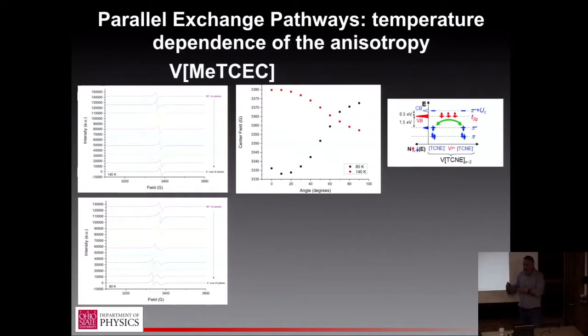Right, and the demagnetizing happens, so it has lots of domains, right? So then the demagnetizing field globally gets much weaker. So it's just not important. It's not contributing much energy to the system. But we still have anisotropy. So this is what I think is our leading explanation: there is actually some residual structural order, maybe even just templated off the hard surface of the substrate, that's producing some real magnetocrystalline anisotropy in the material. What is the substrate? It's sapphire for these samples so that it's happy in the EPR cavity.